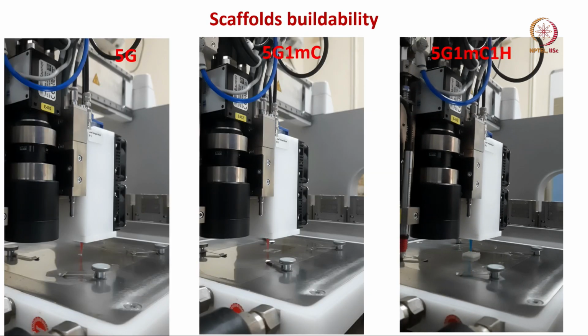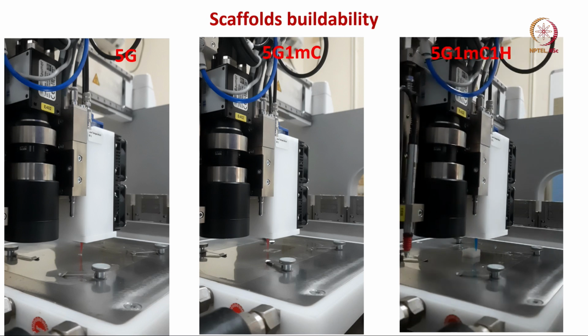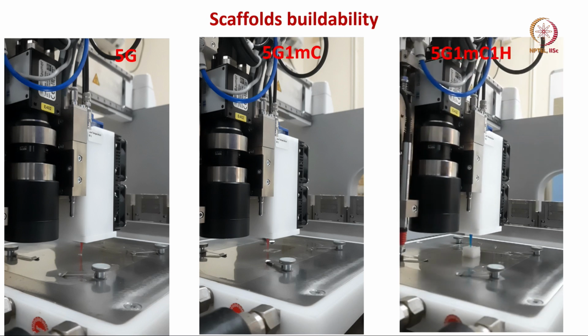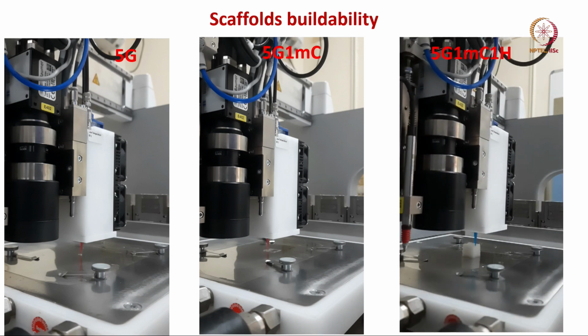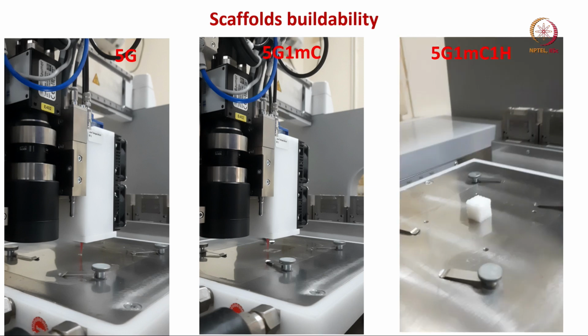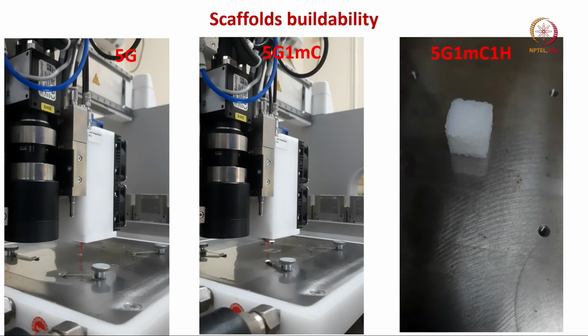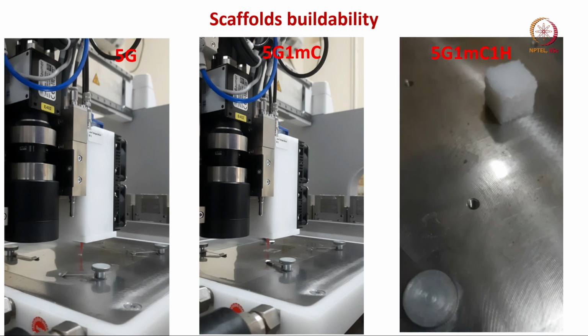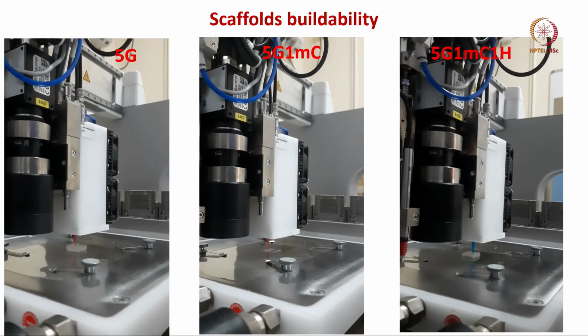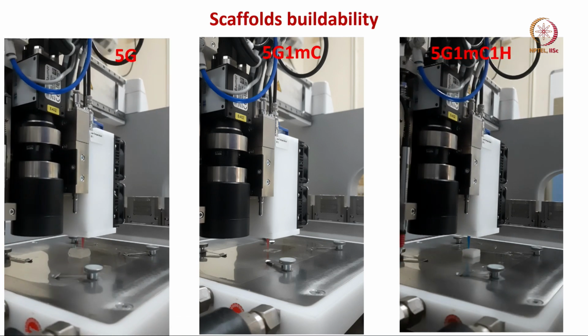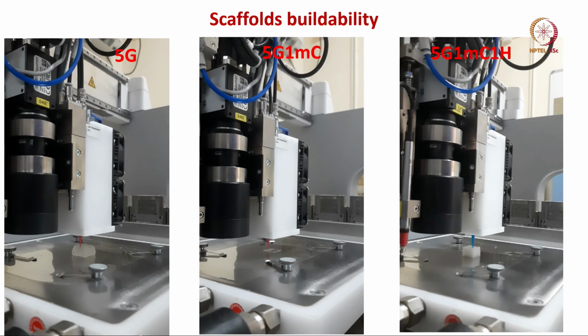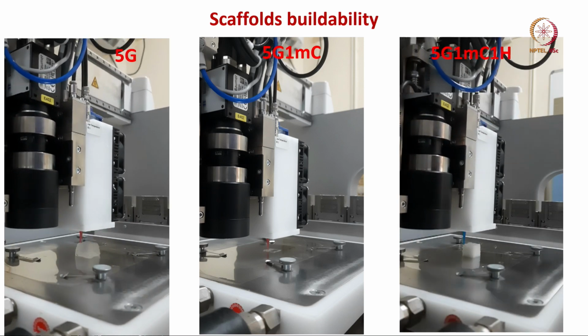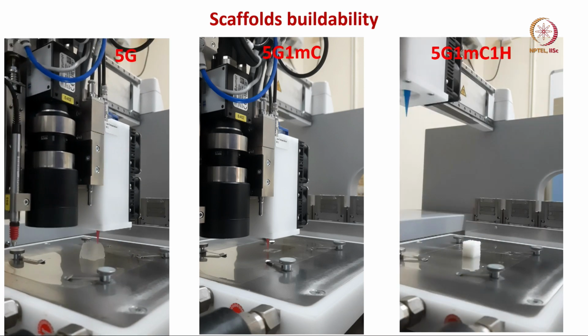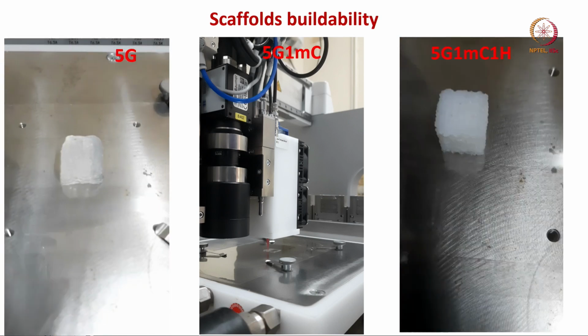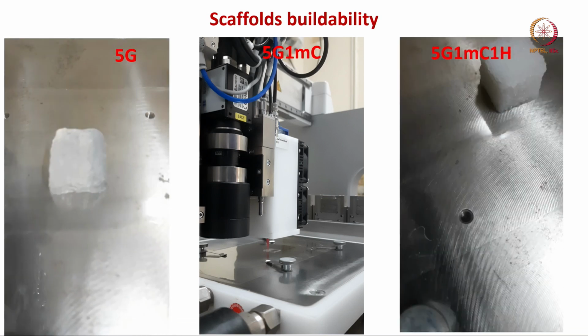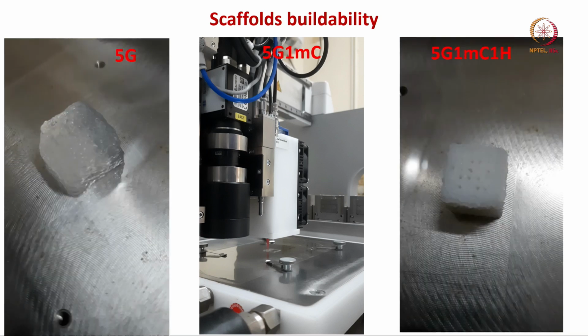Now, you can see how this 5% gelatin, 1% carboxymethyl cellulose and 1% hydroxyapatite is printed to make this construct 45 layers long, and when you have cross linked it, you can see good printing resolution also. Whereas with 5% GelMA, you do not see any shape fidelity. So, it gives you direct evidence that hydrogel modifications allow you to manufacture shape fidelity compliant constructs in this low concentration GelMA system.